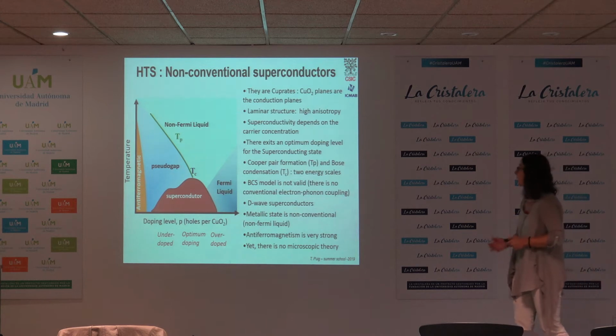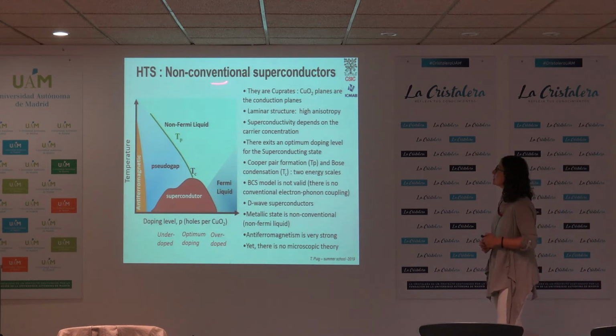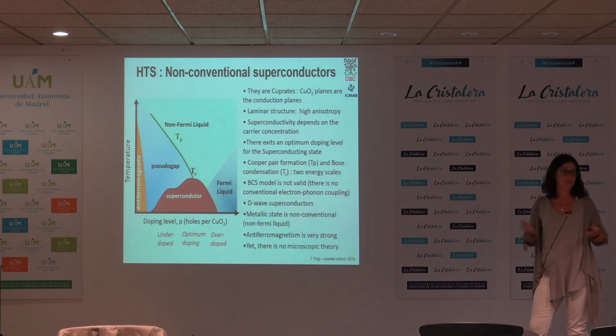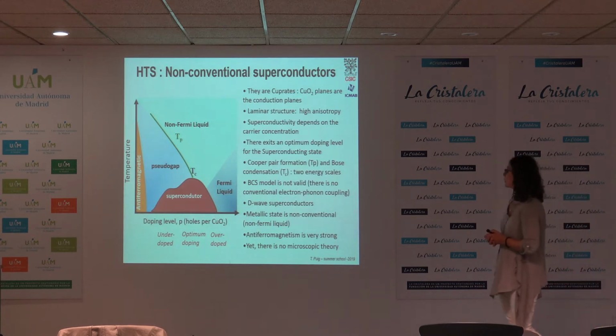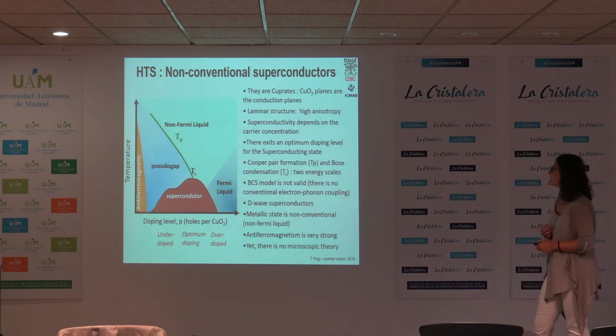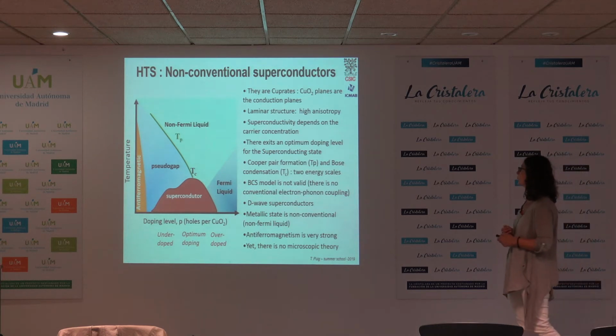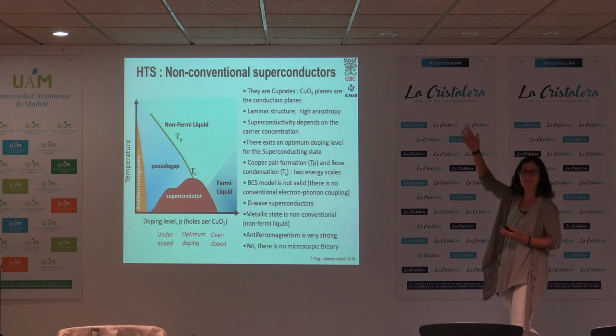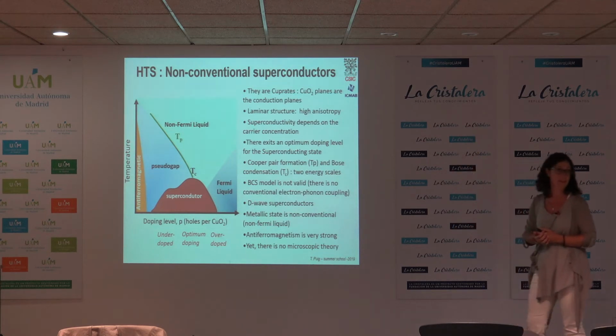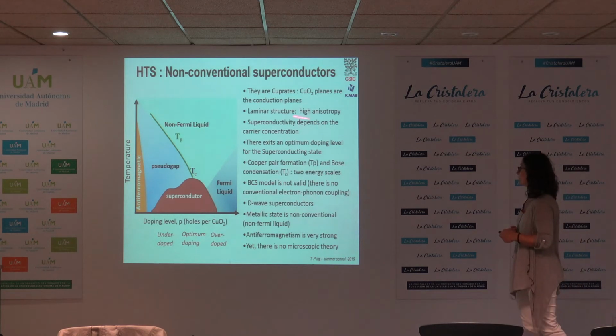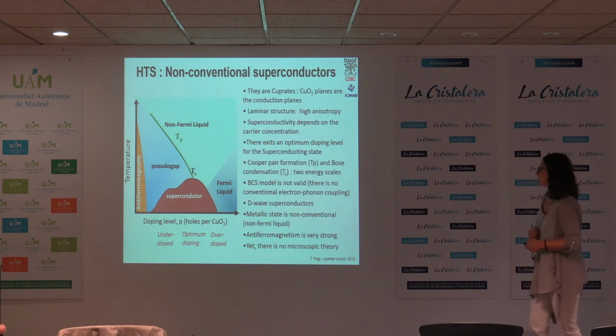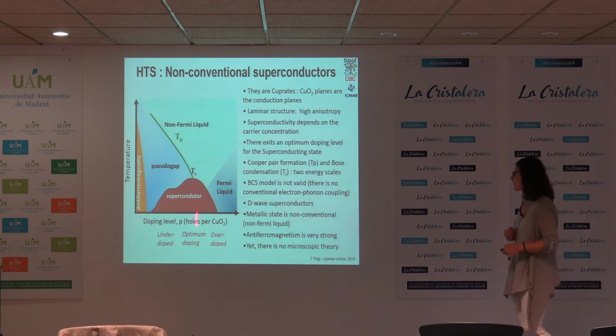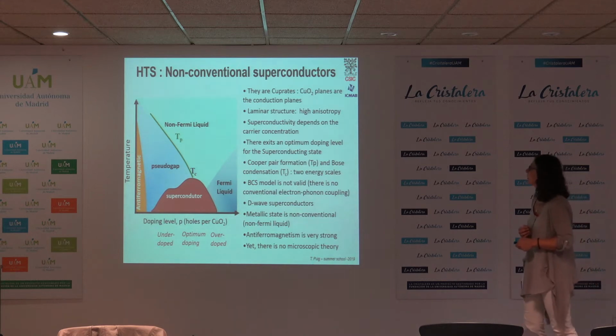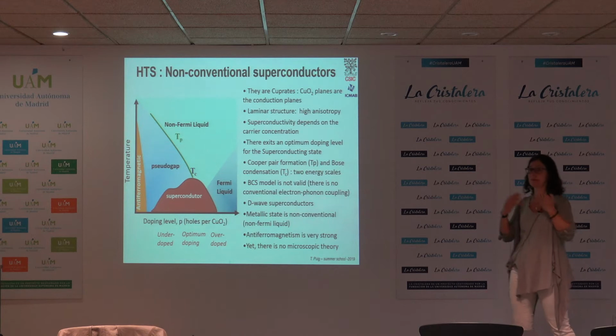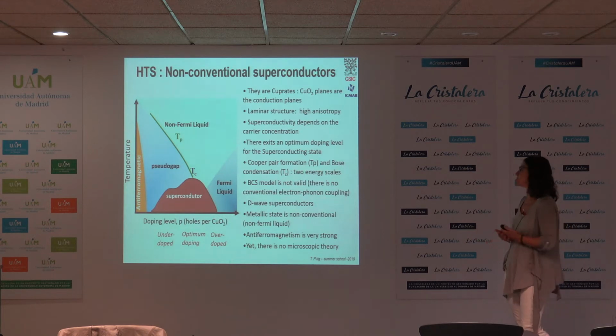Well, I don't have to go through that. HTS is a non-conventional superconductor. I think you have been discussing this quite a lot during this week. But just to remind you that YBCO in particular, or HTS cuprates, are not fulfilling the ideal requirements I put at the beginning, because it's a very highly anisotropic material. It's not easy to fabricate, and it depends a lot on the carrier concentration. It has a high TC, but it has an irreversibility line with a lot of thermal fluctuations of vortices.